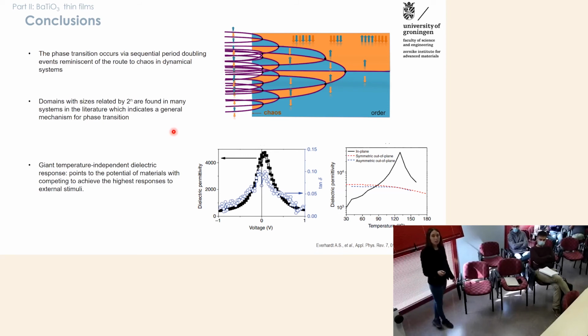And finally, measuring these films with other methods has shown that there is a very high dielectric response in this material, which is temperature independent. So this means that this coexistence between different phases and different periodicities can actually help to make the material more sensitive to external stimuli and can be used for devices or in general applications.